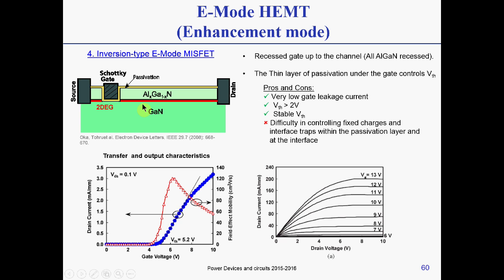And the threshold voltage is quite high because you have a silicon nitride layer, an insulator layer below it, so it's 2 volts. Higher than 2 volts actually, and also very stable. The problem is the difficulty in controlling the fixed charges at this interface. So we said we have charges between the passivation layer and the top layer, charges, by charges I mean traps,